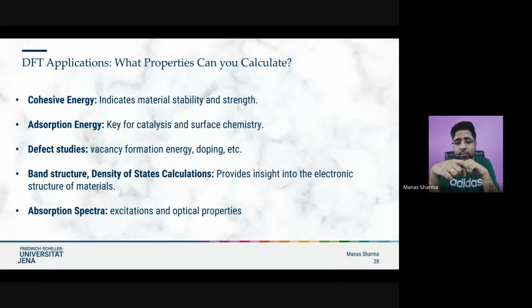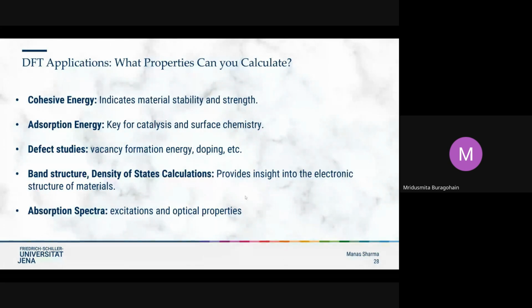And in fact, sometimes you will notice that some functionals are not implemented in the DFT codes, because people are usually coming up with at least 5 or 7 functionals every year. In that case, there is a really good library called the libxc library. This library records each and every exchange correlation functional ever made, and it provides an interface to the DFT codes that I've seen; usually now all the codes employ it. With that, you get access to hundreds of exchange correlation functionals. So you can of course choose whichever functional you like. Okay, yeah, thank you.